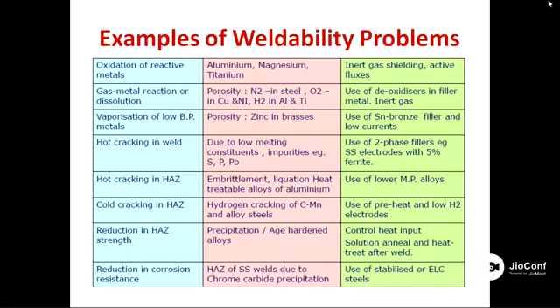The reduction in corrosion resistance, like in stainless steel. Why is stainless steel used? They are used for providing good corrosion resistance. But what if they are subjected to poor corrosion resistance? Then there is no point of using the stainless steel, right? So the heat affected zone of the stainless steel welds, due to chrome carbide precipitation, if this sensitized steel is used for the corrosion environment, it will fail, right? So we have to use the stabilized grade of stainless steel, or extra low carbon grade steel, ELC grade steel. So right, 321 steel, 347 steel, or 0.03 percent low carbon steel, right?